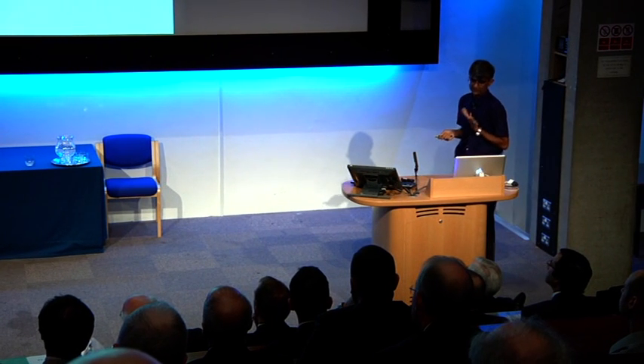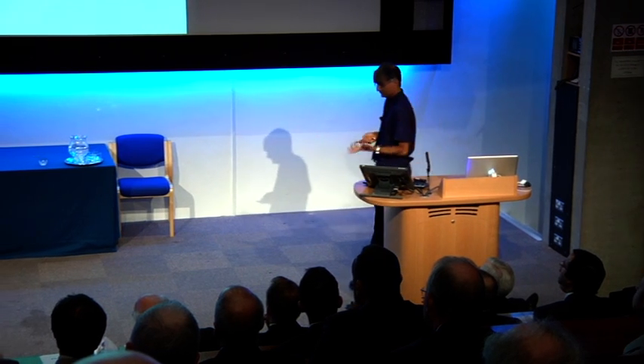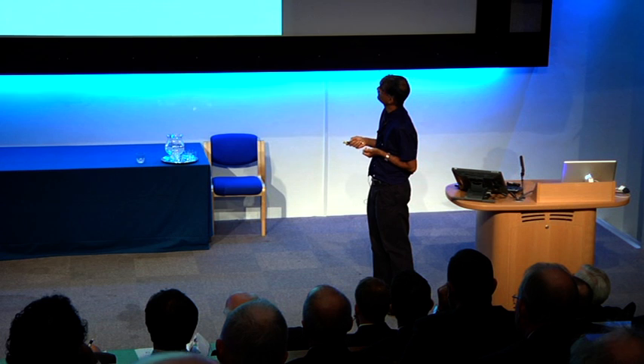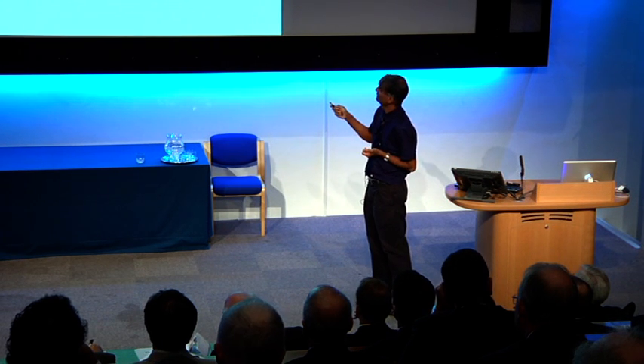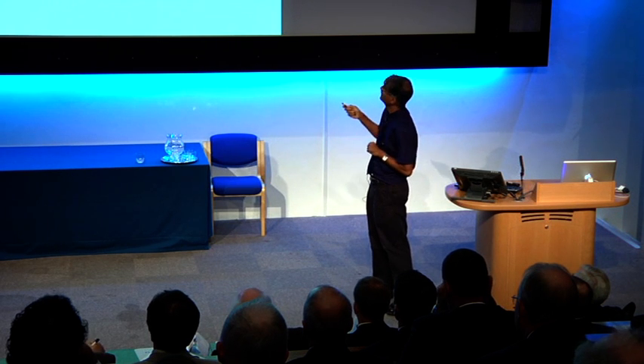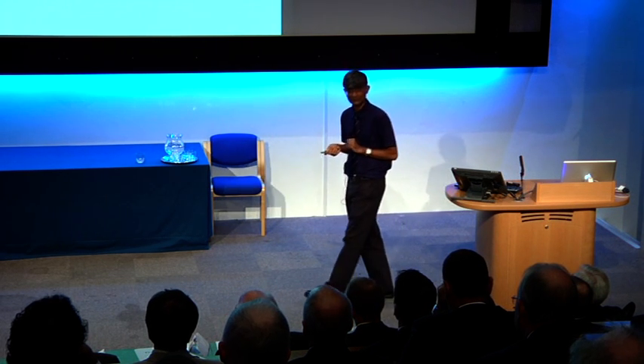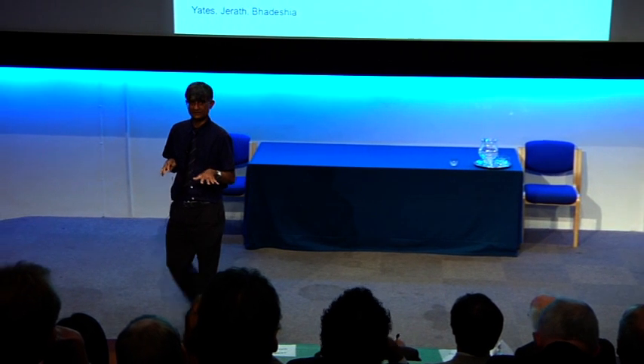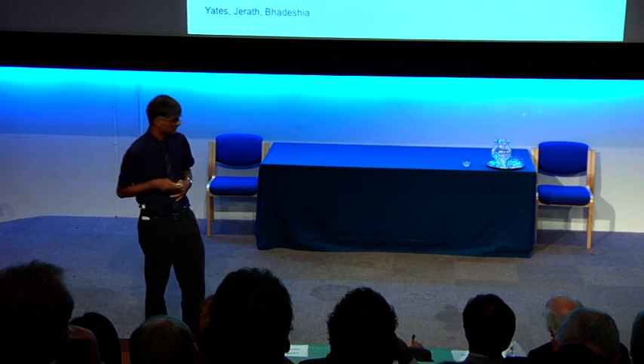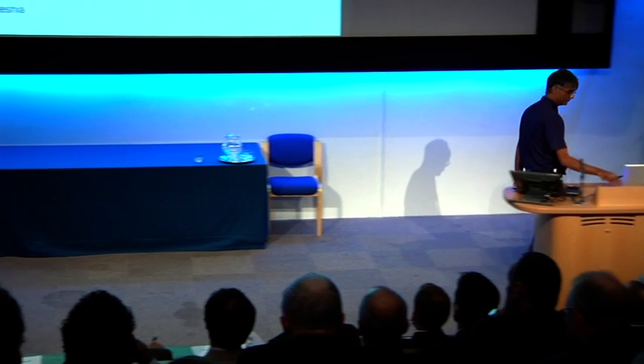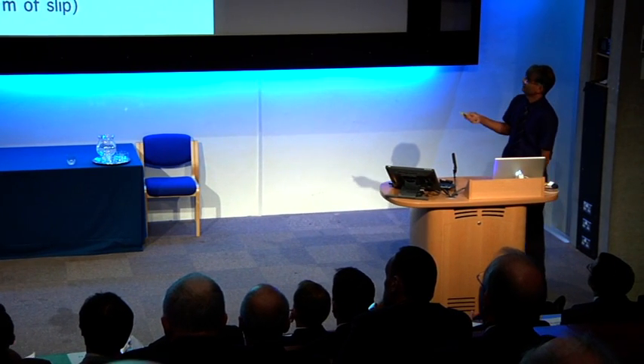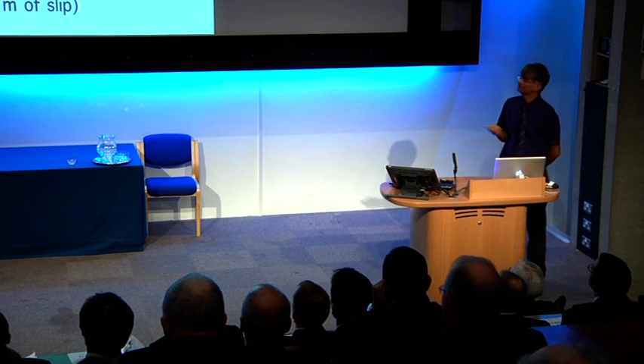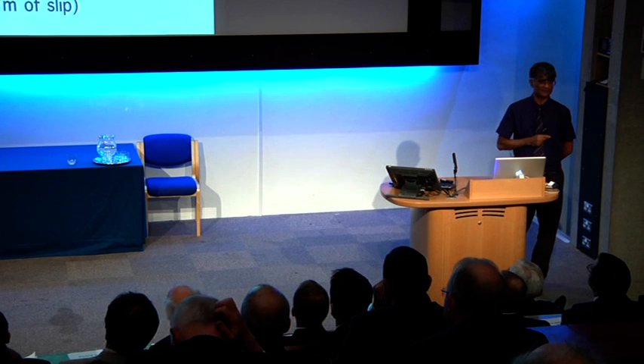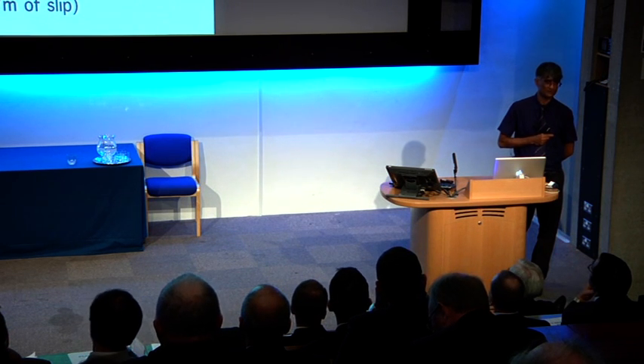Okay, so this is rolling contact fatigue, full-scale tests done at an institute in Poland, where this is the normal rail. Okay, and this is a martensitic hardened rail, and this is the new structure without any carbides at all. So it completely outperforms anything on rolling contact fatigue. Of course, rolling contact fatigue in a rail scenario is different from rolling contact fatigue in a bearing, because there's also a certain amount of sliding involved. In terms of wear, and this you might be surprised, it's minimal wear compared with pearlitic or martensitic, and not only that, but it cuts down the wear on the wheel. It's the only material which cuts down the wear on the wheel.